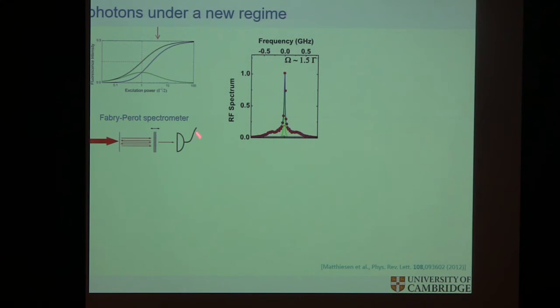And basically what it shows is that if you excite the system at rather strong levels, the spectrum of light that's emitted by a single atom has a Mollow triplet profile. It has ears due to the dressed states, the strong coupling that you have between the laser and the system, and you get a bit of a component on top that looks just like a laser. Just to make it clear, the residual laser, the leftover laser we couldn't remove in the system, is down here. That's the residual component, its power. The rest is actually coming from the scatter.